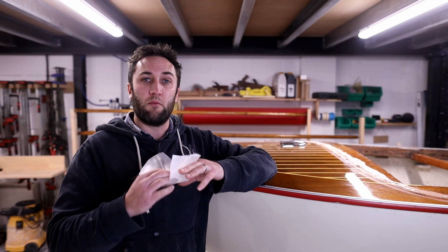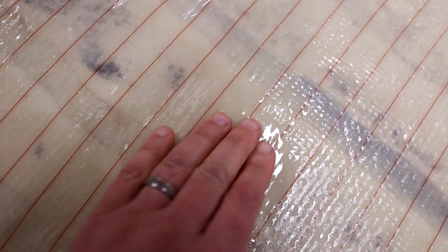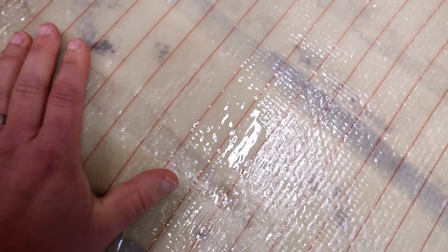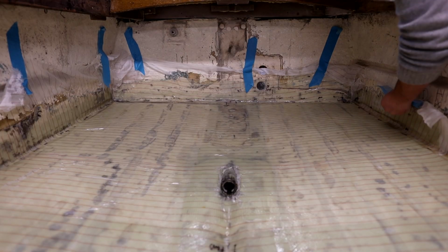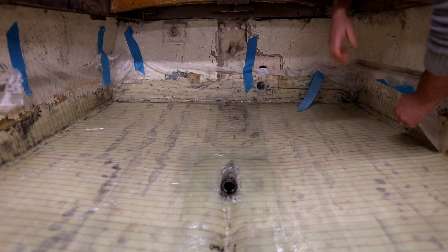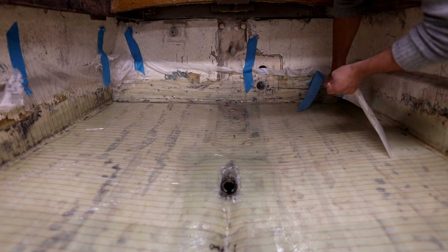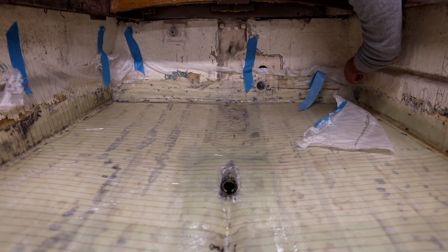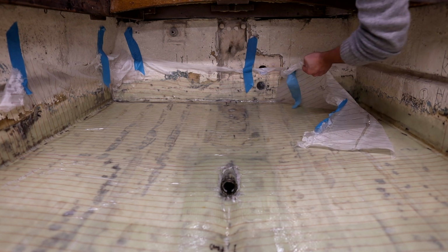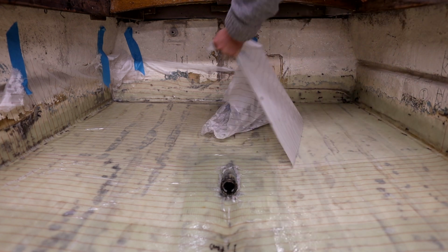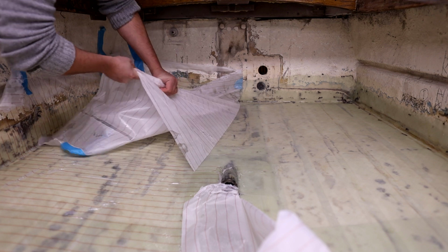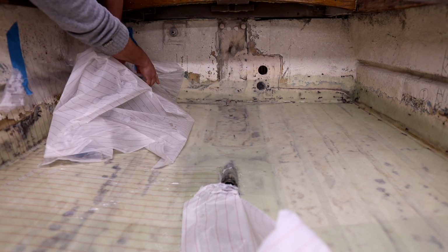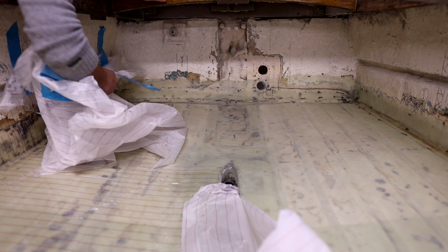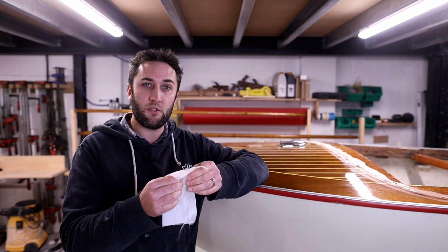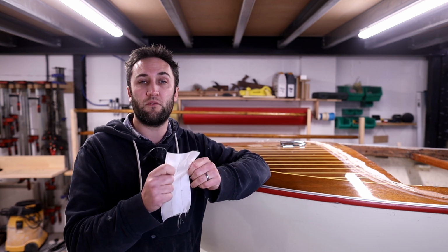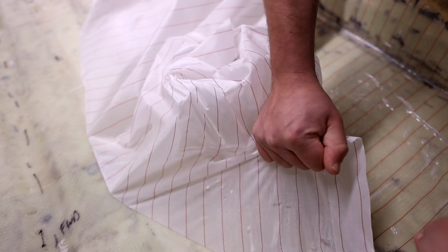It also removes all of the amine blush, which is a waxy substance that comes to the surface of the epoxy resin as it dries. So because you peel away the peel ply, the blush is on the top side of that and it comes away with it. The peel ply also leaves a slightly textured finish behind, which means that the surface doesn't need to be keyed if you've got further bonding to do to that surface.